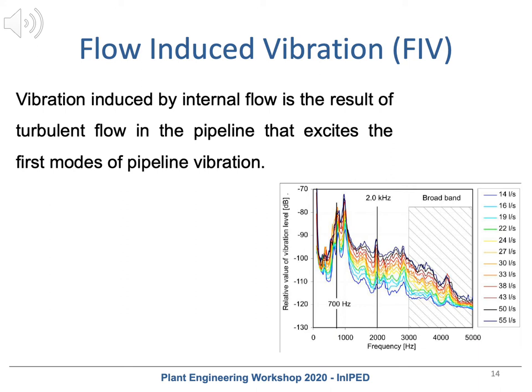Flow-induced vibration is the result of turbulence in the process fluid, which occurs due to major flow discontinuities, such as vents, tees, partially closed valves, and small bore connections. The high level of broadband kinetic energy created downstream of these sources is concentrated at low frequencies, generally less than 100 Hz, and can lead to excitation of vibration modes of the piping and connected equipment.